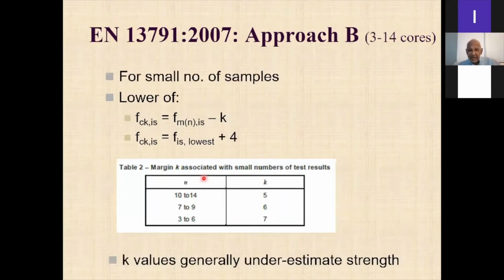Now, if you have less than 15 cores, the formulas are similar to what you have there. Once again, you find the mean strength, right? And you subtract. Now, the standard deviation is not there because there aren't enough cores to find the standard deviation. So depending on the number of cores that you take from between 3 to 14, your K value will be very high here, but less here, right? So this will be the computed in situ characteristic strength. But also, if the lowest strength plus 4 is smaller than this, then you have to take that one, right?